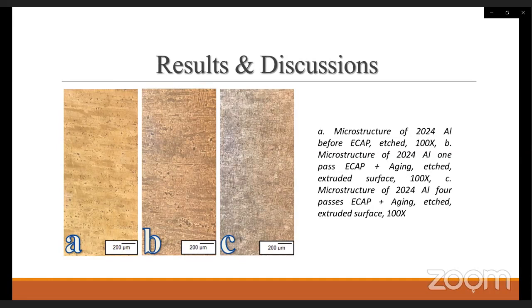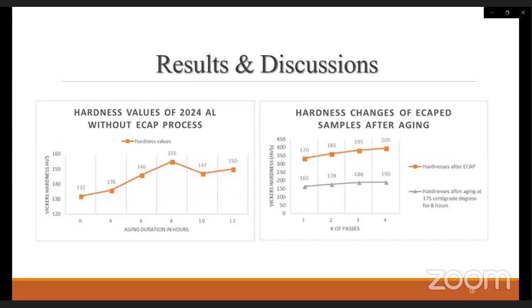So on the right side, which is indicated as C, this is a microstructure of the 4 passes ECAP sample. The shear bands are observed more homogeneously distributed along the microstructure. In this case, the grains get almost 4 times smaller with 12 microns grain sizes. And for the graphics of the hardness and number of passes and the hardness and the aging duration,